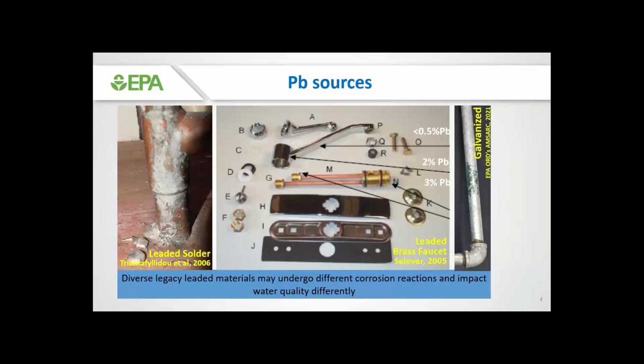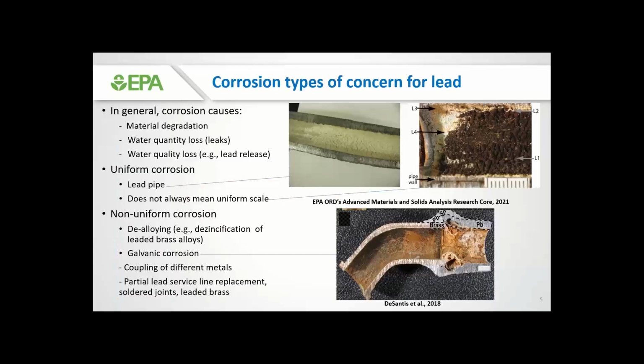Galvanized pipe is also a source of lead. Aside from impurities of lead in the galvanization layer, perhaps its biggest contribution to lead is the fact that it sorbs lead from upstream sources and then becomes itself a source of lead and desorbs that lead back into the drinking water. Because these different diverse legacy leaded materials may undergo different corrosion reactions, interact with the water chemistry differently, and result in different levels of lead contamination, it is important to have an understanding of exactly which lead sources we have in our system.